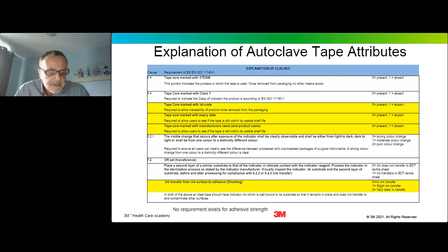One of the requirements of this standard is that the colour change that occurs should be clearly observable, and it should be either from a light to a dark colour, a dark to a light colour, or it should be from one colour to a distinctly different colour. So this is so that users can clearly identify processed from non-processed tape. And that is very important when end users are trying to interpret whether or not the pack has in fact been through a process. There's also a test for offset or transference, and this describes a method for determining if the ink will lift off the surface of the tape and transfer to another surface.